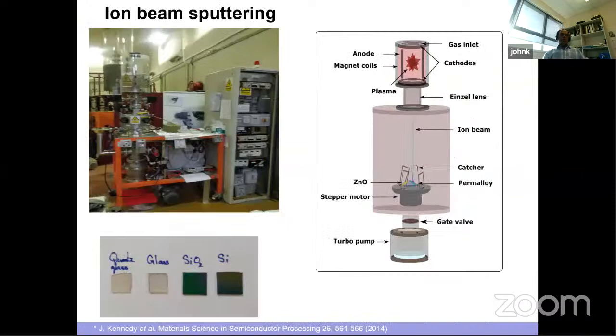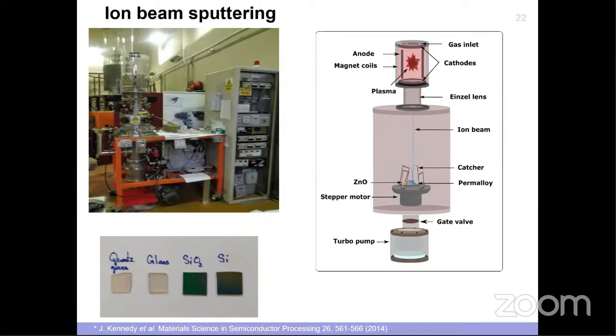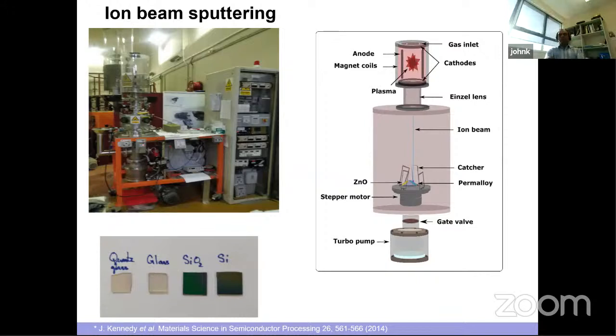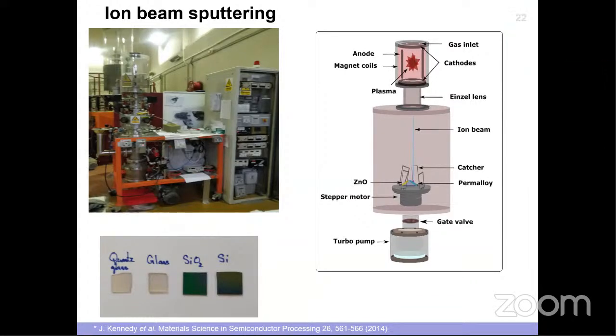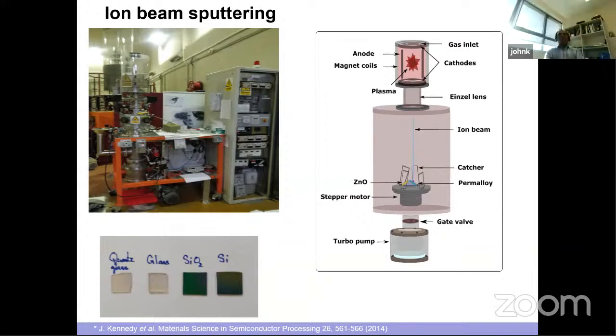So we have been working on making thin films. As I said, the final product we are hoping to see is coating a glass window at home or in commercial buildings to harvest energy. So we use a technique called ion beam sputtering, where essentially you use a small ion source and hit the target, in this case the copper iodide target. Then you sputter it, and you have a substrate as a catcher to deposit onto. The biggest difference is we use 20 kilo electron volt ion beams. So the sputtered atoms come with an energy of a few hundred electron volts, which means your film is atomically bonded to the substrate. So there is no peeling effect. And as you can see, the films are still transparent.